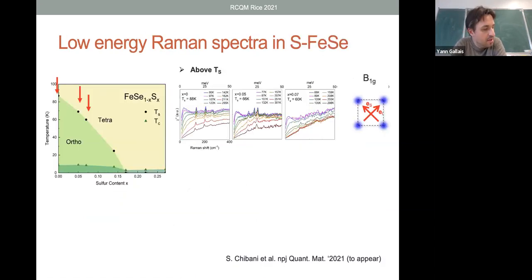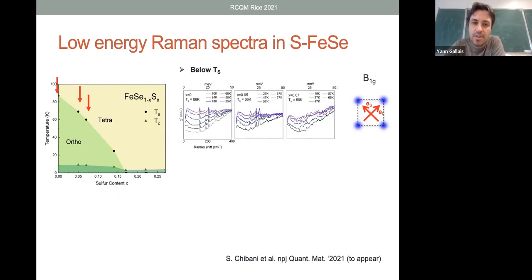Okay, so let me look at the evolution of this nematic fluctuation spectrum as a function of sulfur. So those are the data, again, at low energy, focusing on this quasi-elastic peak as a function of sulfur in the low sulfur concentration part. So you can see in all these concentrations an increase upon lowering temperature. And once you cross TS, which is finite in these 3 samples, there is a collapse. So the evolution is consistent with the one found for pure iron selenide.